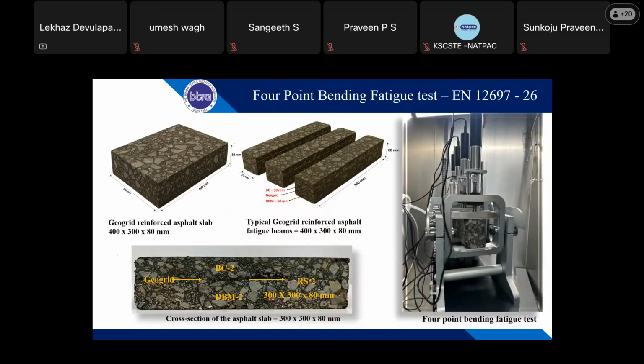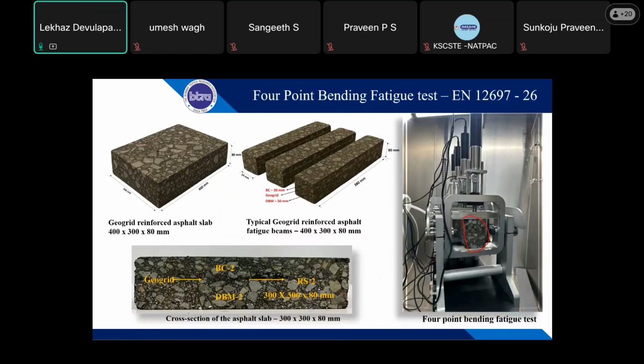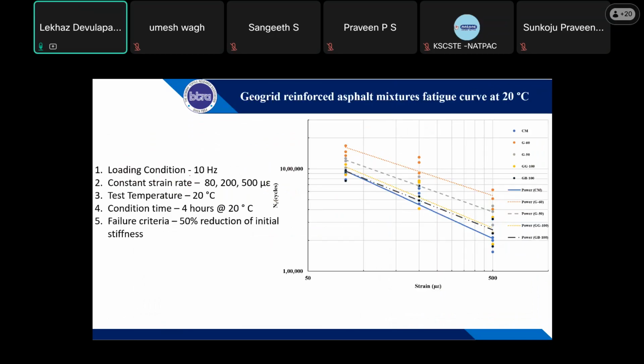And this is how the specimens have been made. We made a slab with the asphalt reinforcement, with the grid, the BC and the DBM. After that, the slabs are placed here. You can see the load is applied at 2 points at the midpoints, with a constant frequency and a constant strain rate. The loading condition was 10 hertz. The test is run at constant strain rates of 80, 200 and 500 microstrains. First we do the test at 80 microstrains, and we see after how many cycles the specimen breaks.